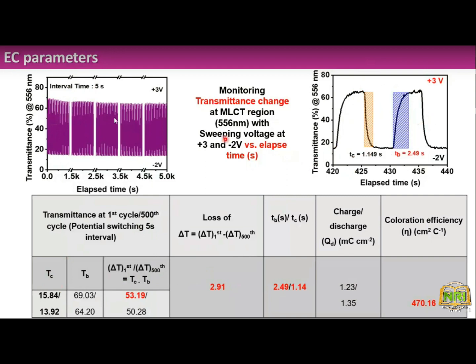And when we are constantly applying this voltage, it is going down like this after certain cycles. I have run up to 500 cycles. What is the loss of that? We can see it is slowly going down, but the loss is only 2.91, which is very convenient compared to other reported compounds. And we have calculated some coloration efficiency. I did not show here how the calculation is done. Just remember the coloration efficiency is 470, but previously reported compounds of this kind show almost 300 to 350 centimeter square per coulomb. But here we got a very high coloration efficiency, which is 470.16, which is very good.